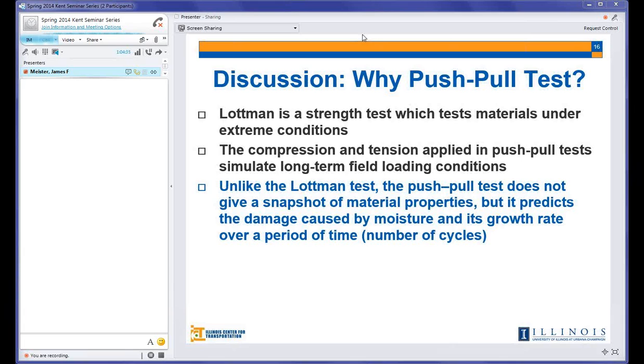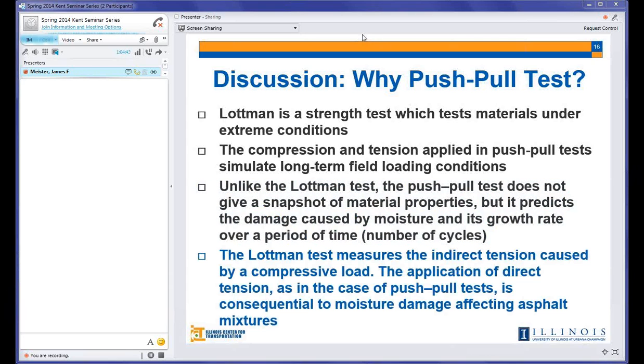You can predict the performance at any behavior, at any macro strain, at any temperature, and that's something you will never get from the Lottman test. One thing that I kept saying more than one time in this presentation is that you get the tension failure from the Lottman test, but by applying a compressive load. So why don't we go to a test that applies a direct tension test, which is more influential to the asphalt mixture that we are testing for the moisture sensitivity.